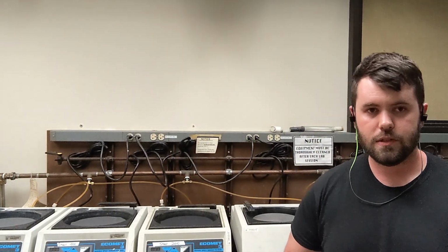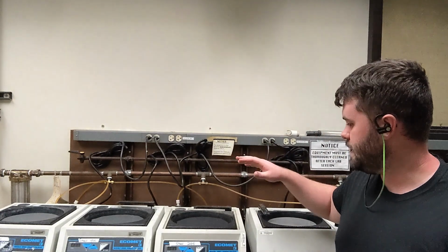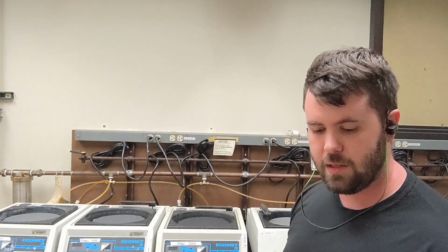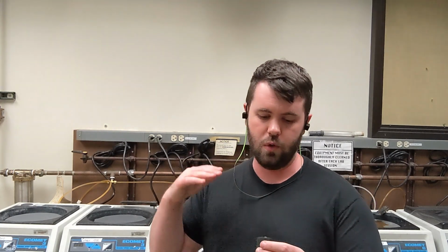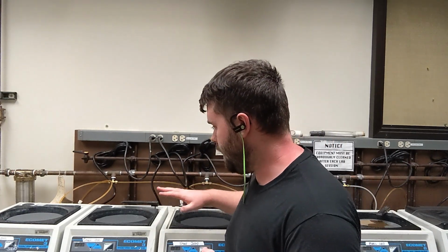So let's go over to the other side of the lab. Here are our 3 polishing stations. Each of these is the same machine. We just put a different sandpaper wheel on top of it. Initially, when we section our sample, the abrasive blade from the cutoff saw does a lot of local damage to our sample. It heats it up, it gums up the metal a little bit, it scratches it really severely. So in order to get to our mirror finished final surface, we need to remove the damage from our abrasive saw, and then each of the 3 machines has a less rough sandpaper pad.